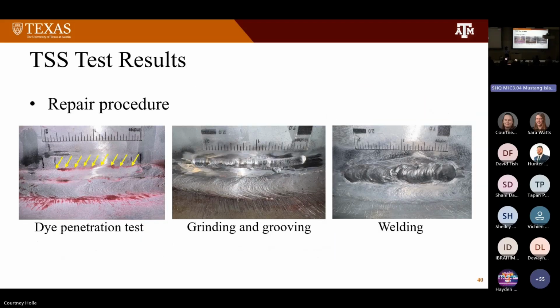Before we start the repairing process, we wanted to double check the crack location by doing a dye penetration test. It is one of the non-destructive testing methods, so we spray the visible dye, letting it penetrate into the surface defect. Based on the penetrated dye, we can check the crack location as shown on the picture. After this, we ground and grooved the location, then welded it.